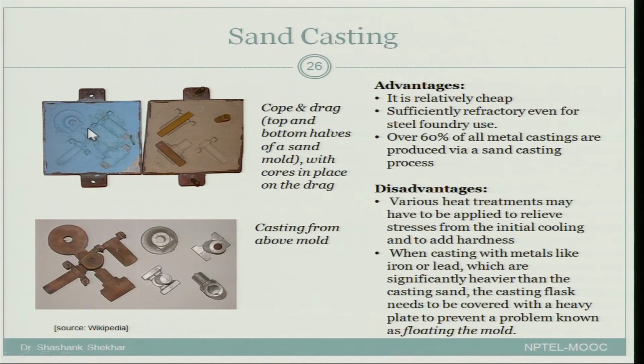So you put it back and then you pour the liquid in it, and the liquid will go inside and fill all those hollow regions and you will get something like this. So these are the 4 components put together along with the sprue and the pouring basin, you can see over here, and when you cut it off, when you separate it, you will get these 4 casting components obtained from the above mold.